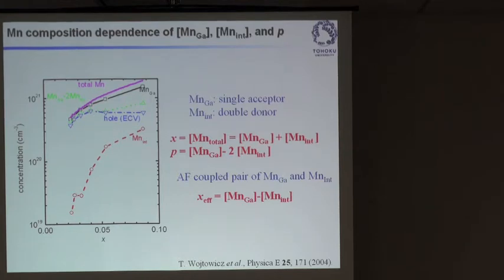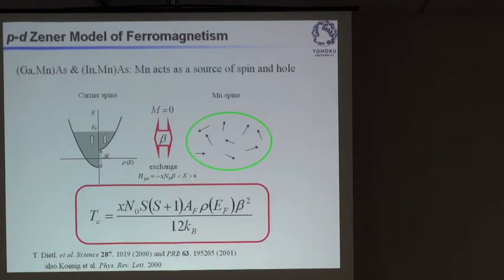So we can now develop a model for the ferromagnetism we see in the system, which was actually done with Professor Dietl, who is in the audience. So this is our model. We have two spin systems. One is manganese spins; basically, these are manganese d electrons. And these are carrier hole spins. And we assume here that we have an exchange interaction between these p electrons and d electrons. So we call it a p-d exchange, which will be the subject of Professor Dietl's lectures this afternoon.